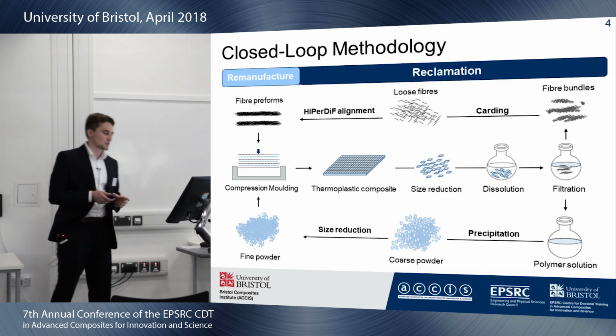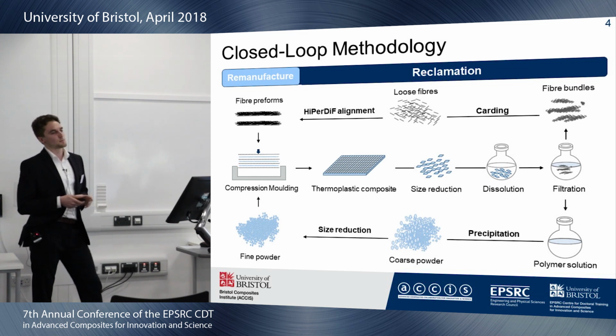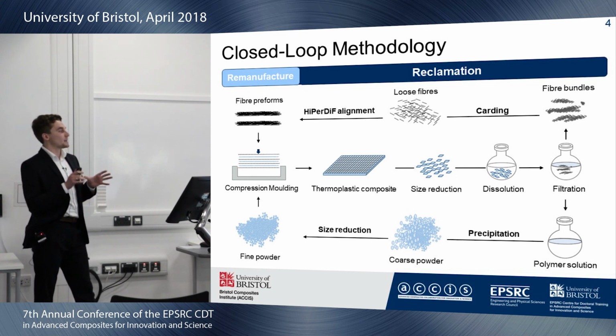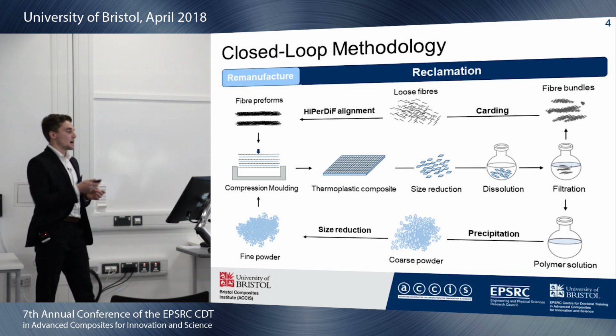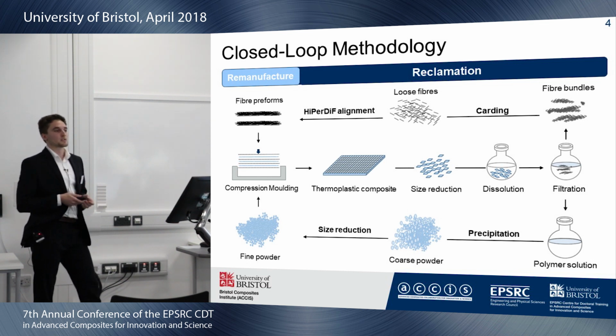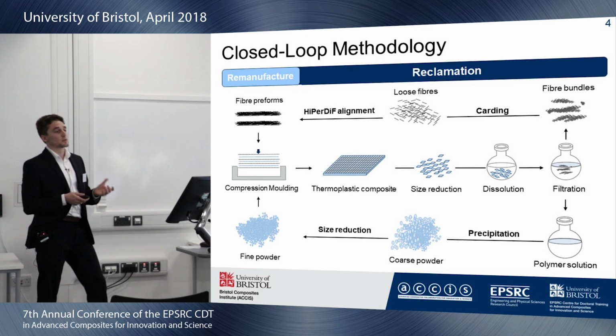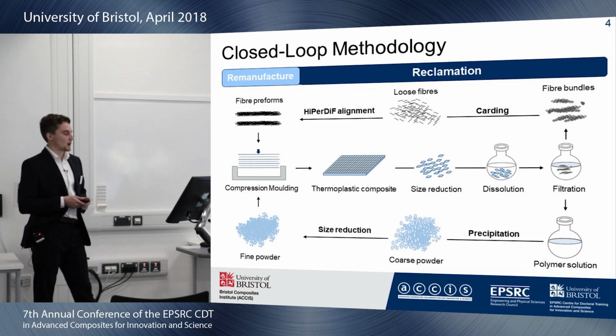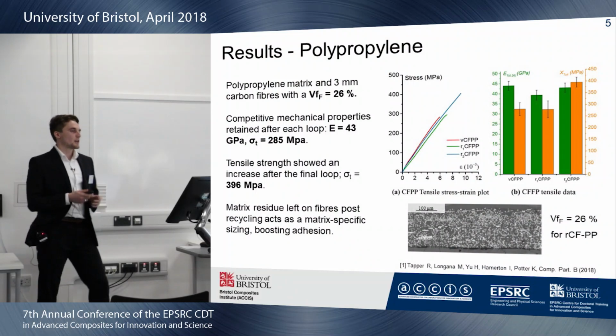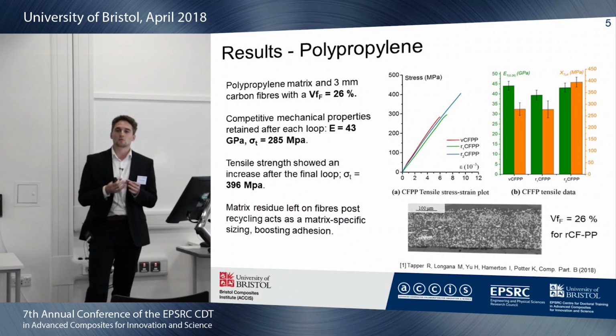So then with the polymer solution, I precipitate out the powder and process that into a fine powder, and that really encapsulates the reclamation process, which is half of a recycling process, reclamation and remanufacture. That part of the process, you take your preforms and you just do simple compression molding to make your composite part again. So currently, this has all been proof of concept, and I've made some small specimens to test.